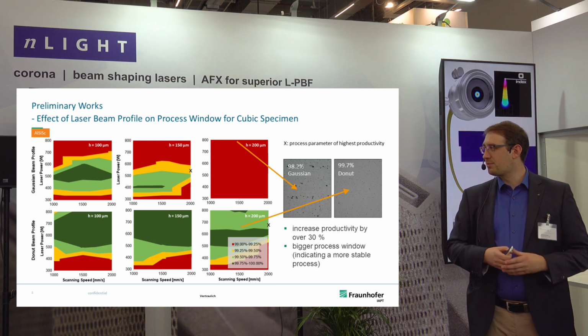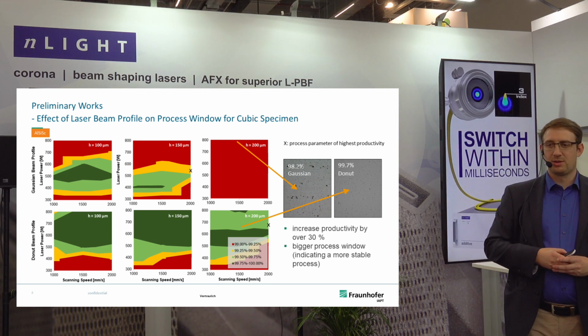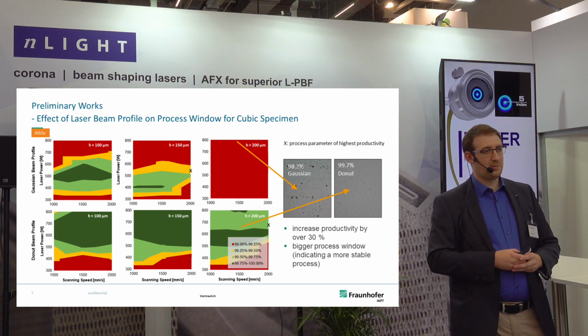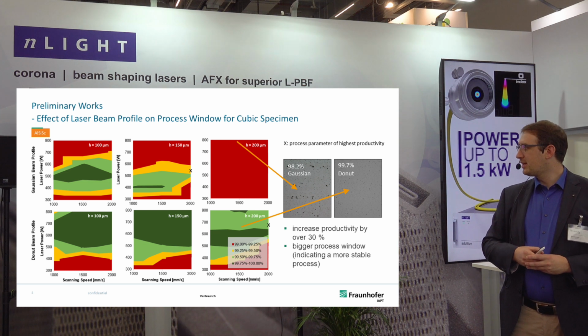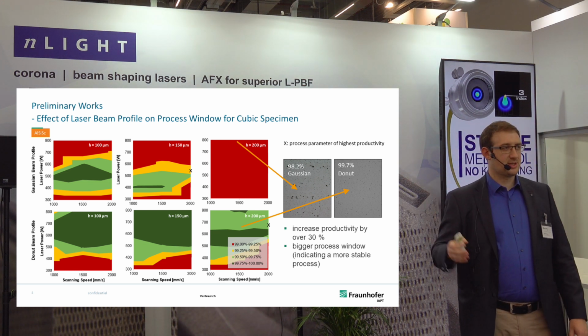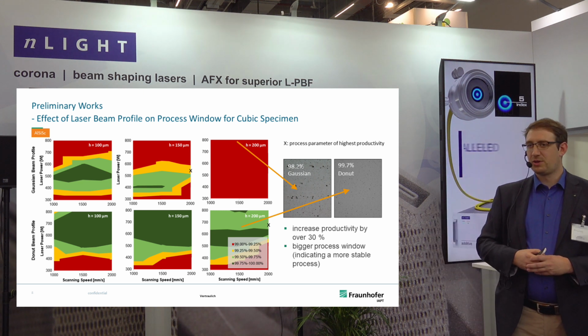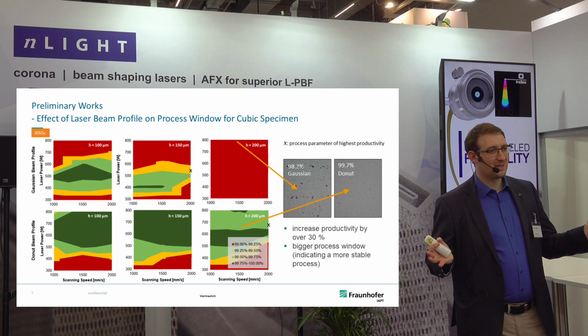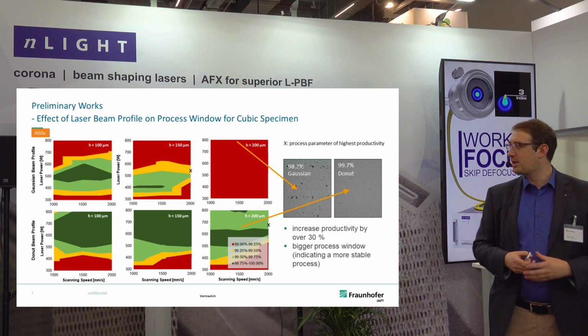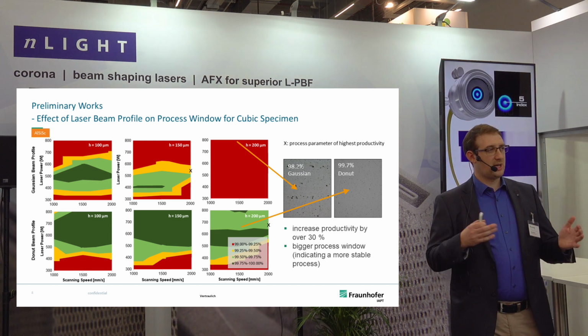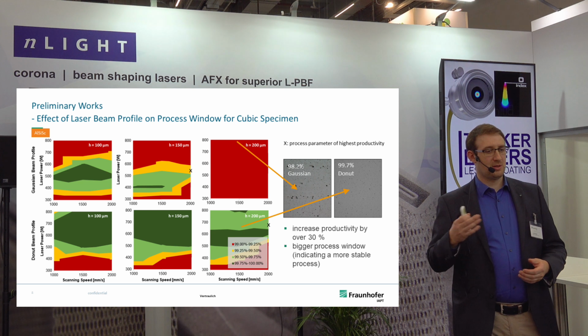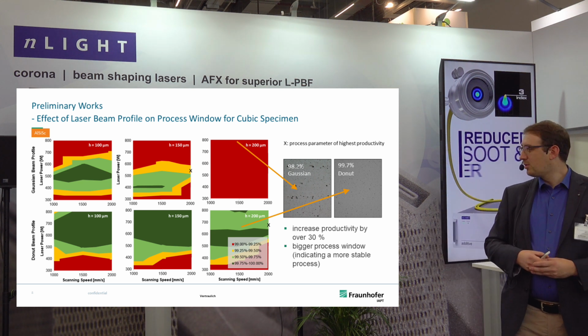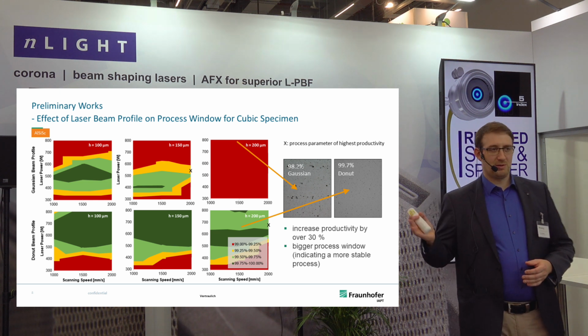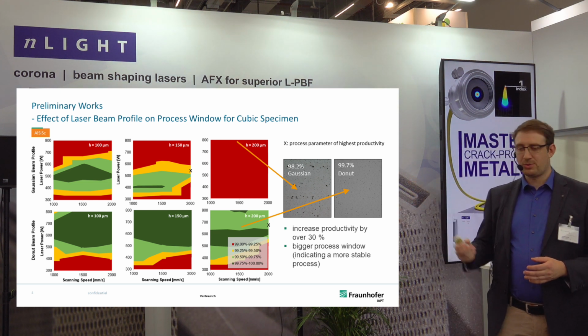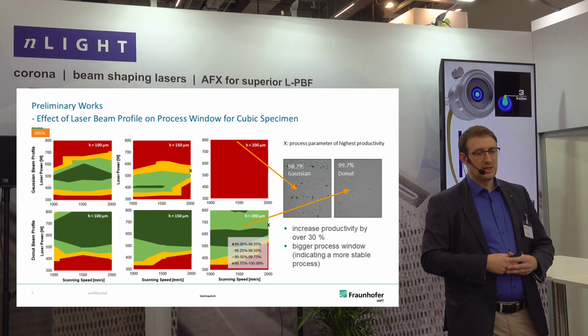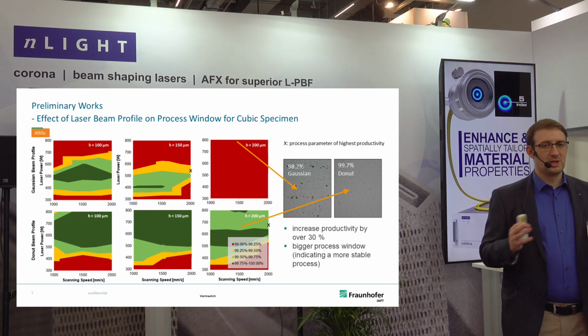You can see that for different parameters, on the top for the Gaussian beam profile and on the bottom for the donut profile. A very interesting part is that the H stands for the hatch distance, the distance between two tracks. If you look at the top right graph, it's red. So for this particular hatch distance of 200 micrometers with the Gaussian beam profile, we were not able to reach a final part density of better than 99%. While for the donut beam profile, very spectacularly, we get regimes with almost 100% density, and this is a very big difference between the two beam profiles.